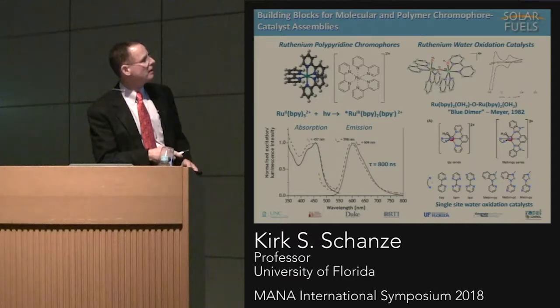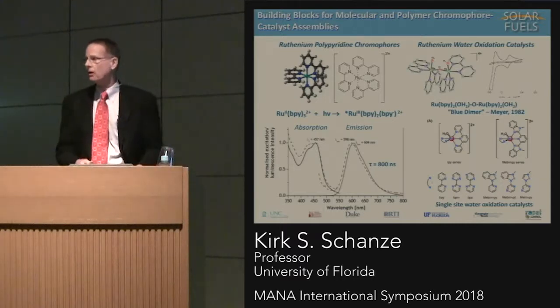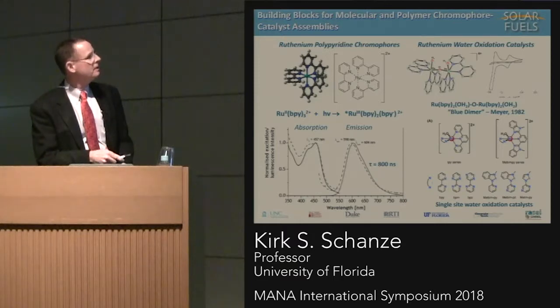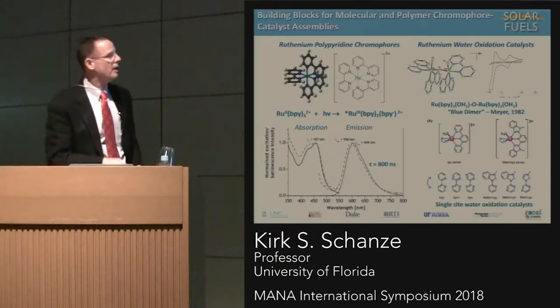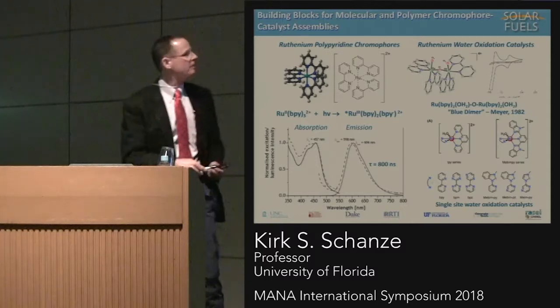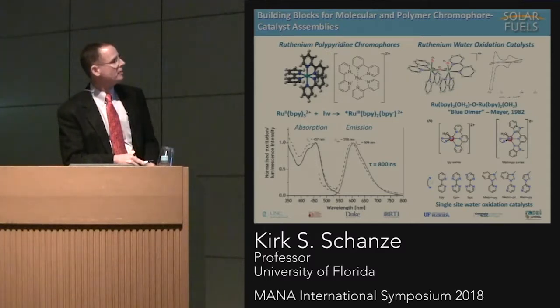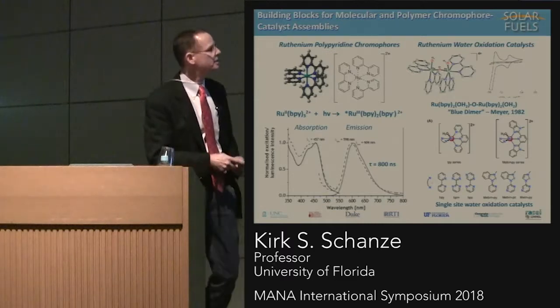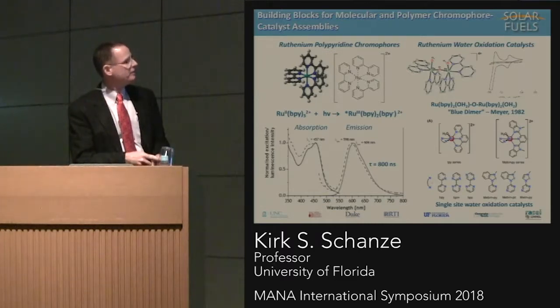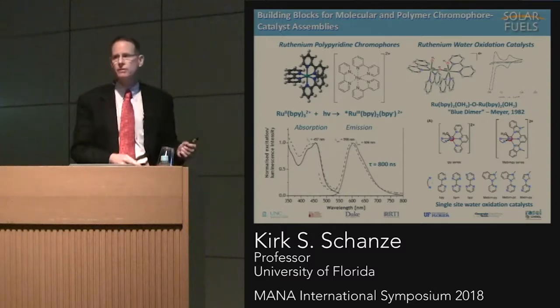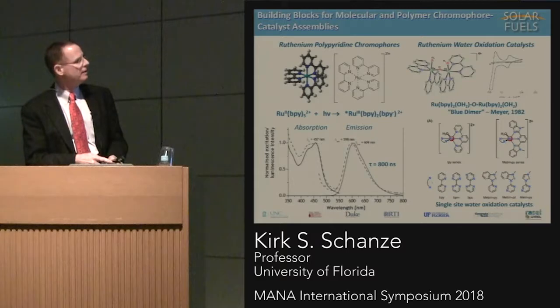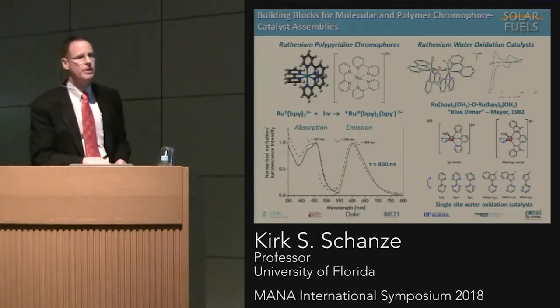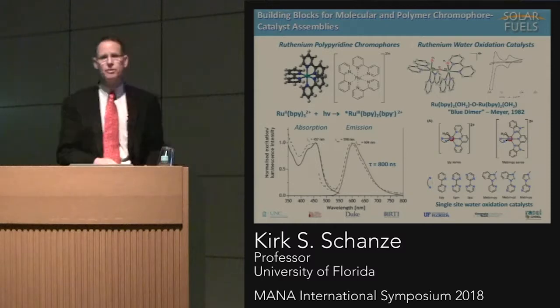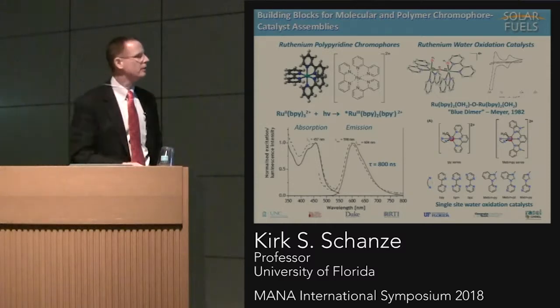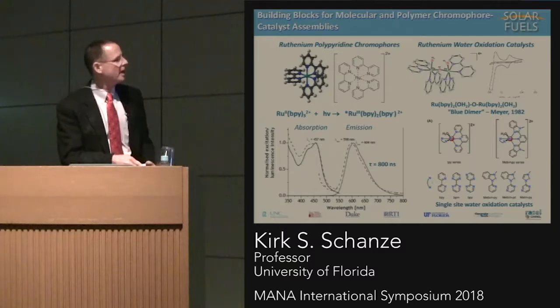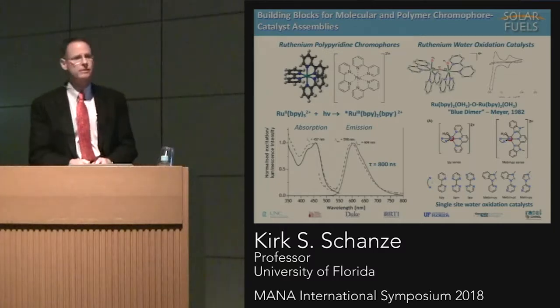Less well known is the fact that there are a number of ruthenium complexes that can also serve as water oxidation catalysts. The first example of one of these systems was developed by Tom Meyer, the director of our center, and that's a ruthenium dimer complex that was reported back around 1982. During the 90s and more recently, there have been a number of what are called single-site water oxidation catalysts, and these are ruthenium compounds that contain only one ruthenium center, and these also can accomplish water oxidation with varying turnover numbers and turnover frequencies. So again, I'll be talking some about these types of catalysts as we go forward.